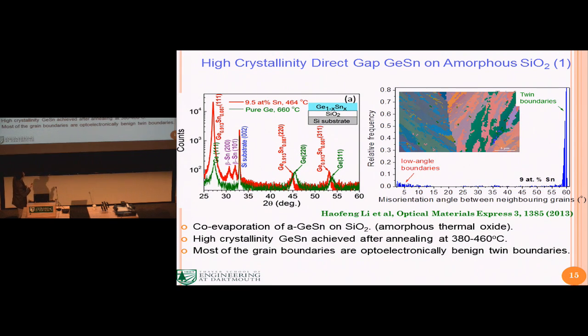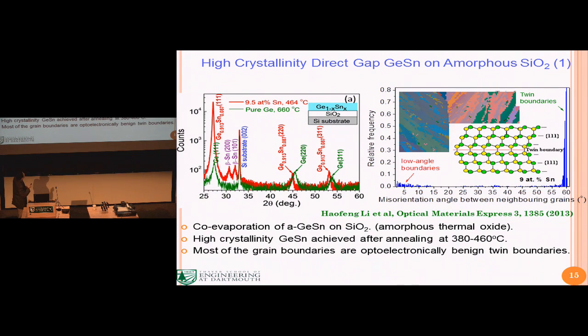Another interesting thing is that if you do statistics on the misorientation between the grains, you'll find a very concentrated misorientation at about 60 degrees. Those correspond to what we call the twin boundaries. A twin boundary is basically like a mirror, where on both sides of the mirror, you get the mirror images of the crystal. It's one side like this, the other side like this. The important thing is that across this interface, there are no broken chemical bonds. So that's why the twin boundaries have very benign optoelectronic behavior. It doesn't really introduce defects in the semiconductor material.